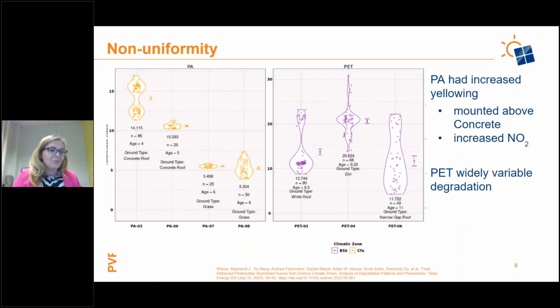And interestingly, when you look at the yellow here for polyamide modules, we saw two modules, PA3 and PA6, which were taken from the same climate zone, CFA, and had similar years of exposure. These are measurements of yellowness index on the same exact module, just at different points all over the module. You'll see that yellowness index varies greatly over the whole backsheet. And so what you see here is non-uniform discoloration and degradation over the scope of the module.